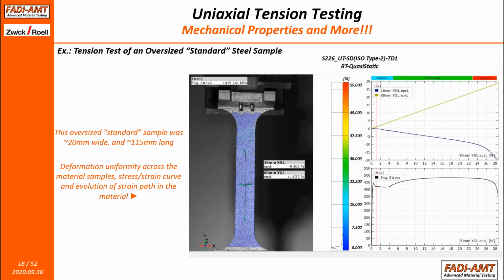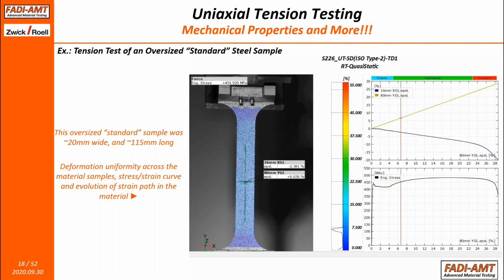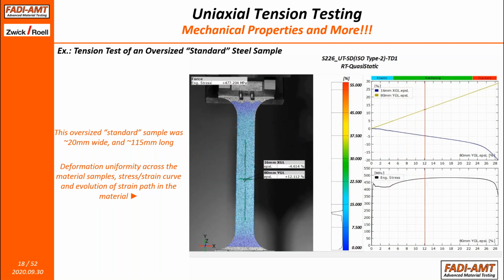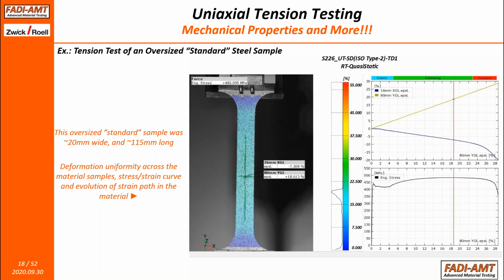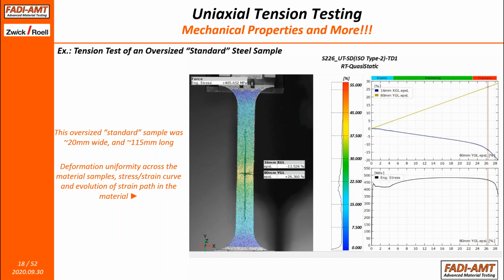So now let's go to the other side of the spectrum, which is larger sizes. When do we need to do this kind of testing with samples that are larger than standard? This is technically still a standard sample. It's a 20 millimeter sample. It's a European standard versus the North American one. So it's larger, about 20 millimeters wide, about 100 plus millimeters long. And this can be definitely done with conventional extensometry.